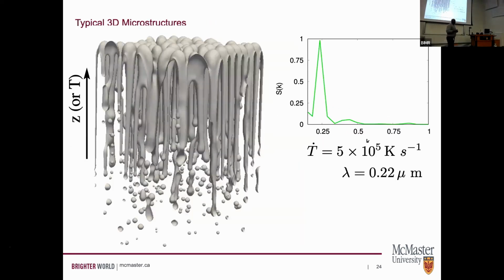We could also look at some of these things in 3D as well. And so the interesting thing about 3D, although we saw it in the 2D simulation as well, is you're leaving behind these rich pockets of liquid as this solid moves and consumes the liquid. Our assumption is that these rich pockets of liquid could potentially form secondary phases further down the line.